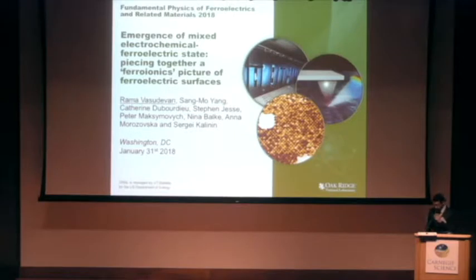So we've seen a number of talks today about interfaces of ferroelectrics. And of course, that's very important. But one of the areas of ferroelectrics that hasn't received the attention that it deserves is the bare surface of a ferroelectric, because a number of quite interesting processes can happen on ferroelectric surfaces, particularly when you start to scale down your ferroelectrics to thin films, for example, of 10 nanometers or so, the surface electrochemical processes can actually have a very large impact on the ferroelectric phase stability, and that's what we're really looking at in this particular study.